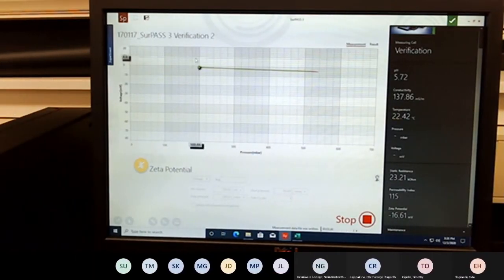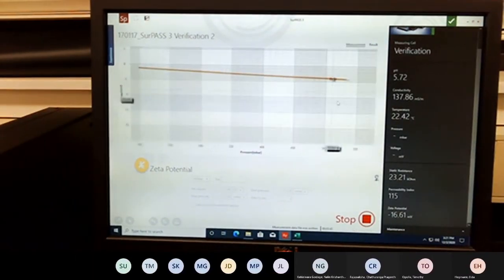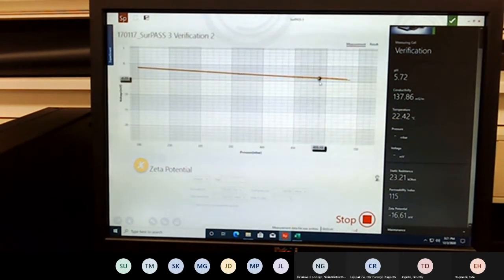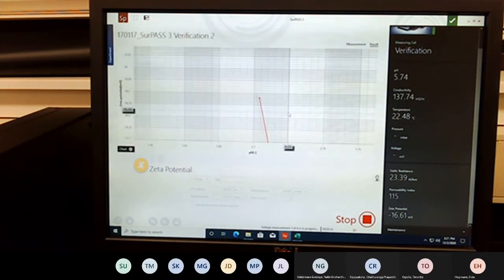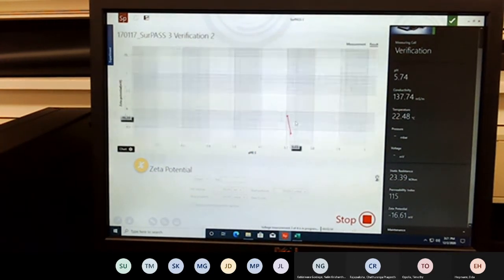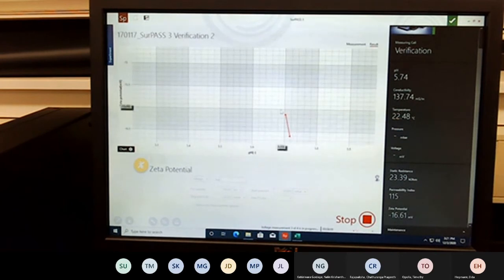So here we have the second run. You can kind of see them overlaying. And this is more or less what you want to see. You want to see pretty vertical curves here, just going from one direction to the other. You can also switch from measurement view to result view to compare the two numbers to each other. I know that looks big in terms of distance, but really it's just 16.1 and 16.5 millivolts. And then you can see some slight changing in the pH, not too much, 5.7 to 5.71. So this is more or less what we expect to see.